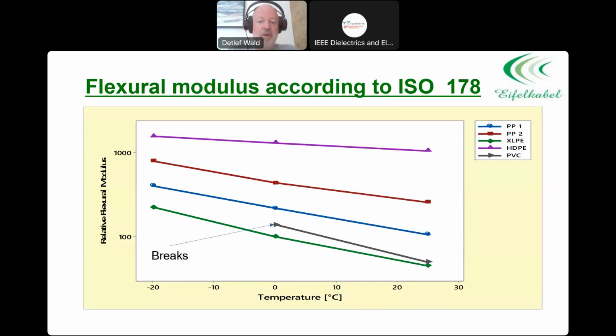So, low temperature brittleness. The issue was here, the test we made, you might ask yourself, why did we only go down to -20 degrees? That was at that time the customer request. In that country, the cables were installed only at -20 degrees. I know that there are certain countries where the temperatures can be lower, like certain countries require -70, but I'm 100% sure at -70, you have other problems when you install cables than just an inflexible insulation.